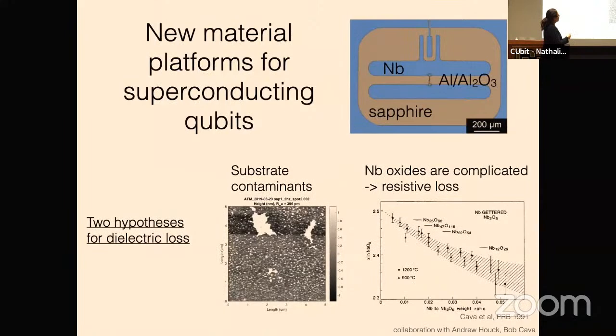So his qubits were niobium on sapphire, and you have aluminum oxide in the Josephson junction. So there were sort of two basic hypotheses for where this dielectric loss could come from. My bias is that everybody has hydrocarbons all over everything, and substrate contaminants play a really big role. And then the other thing that we zeroed in on is that niobium oxides are actually quite complicated and really hard to control. And you can have resistive loss from weird kind of metallic or almost superconducting phases, and then of course a lot of dielectric loss from just very messy oxides.